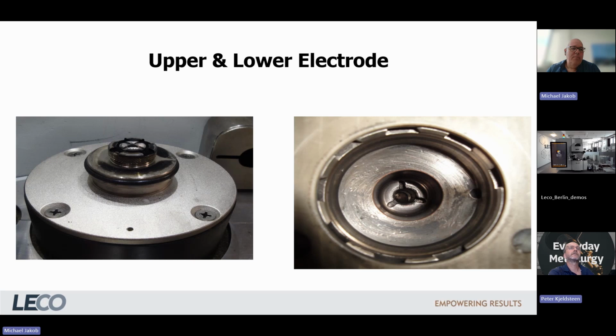Okay. Because I could imagine that if you drill or if you cut it with a grinder, you introduce oxides. Absolutely. And then you disturb your measurement a lot. Absolutely true. That's really a problem if you do oxygen. For nitrogen and hydrogen, normally this is not the case, but for oxygen, yes.